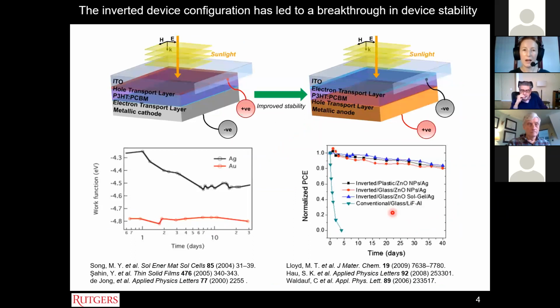So our first study was on the formation of native metal oxides and how they can be used to affect the injection or collection of electrons from an organic semiconductor layer, as well as improving the stability. And of course, the reason you'd want to improve the stability and use silver as an anode instead of a cathode is because silver over time will, even inside a device, form oxides or compounds on its surface that will typically increase the work function, or make it more negative on the energy scale. In other words, it'll be better for matching with the highest occupied molecular orbital of the semiconductor rather than for electron injection into the LUMO, the lowest unoccupied molecular orbital.